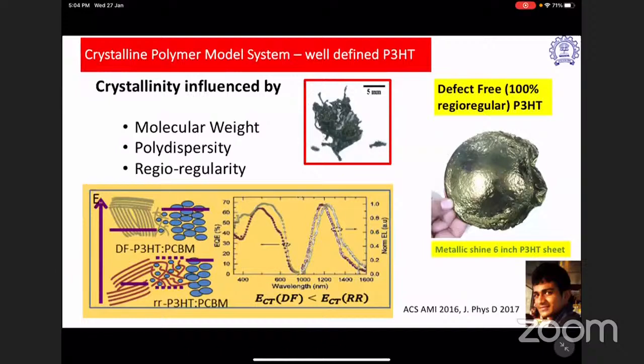how, when you make this phase pure system, you have very good vibronic features and you get much improved performance. When things get phase pure, you see the delocalization of the levels, and that gives rise to a red shift in the electroluminescence. So the electroluminescence and the photocurrent response are both plotted together here. You have those very aligned chains, with fewer amorphous regions, and on the other side you have this wine color, red wine color, with more amorphous regions.